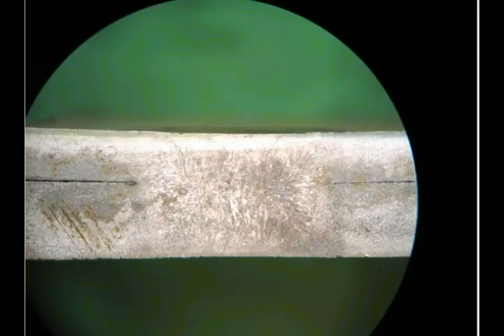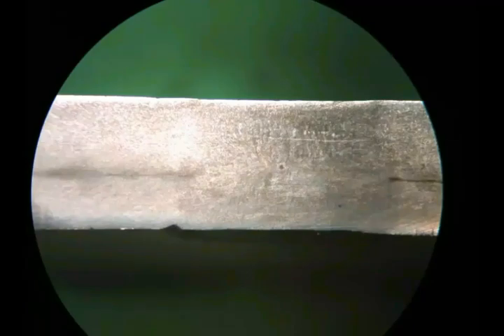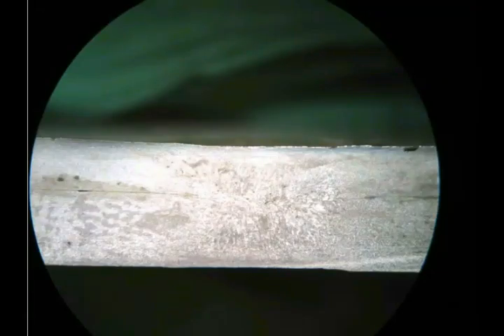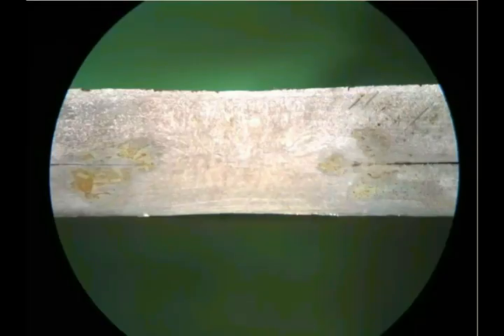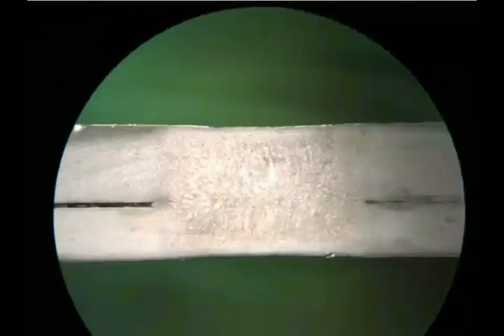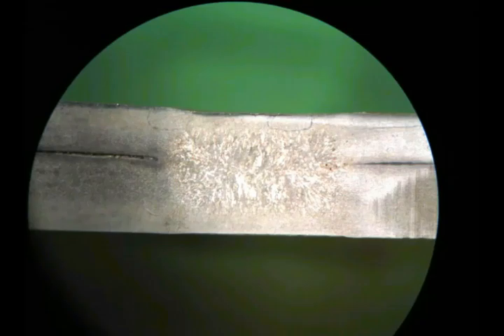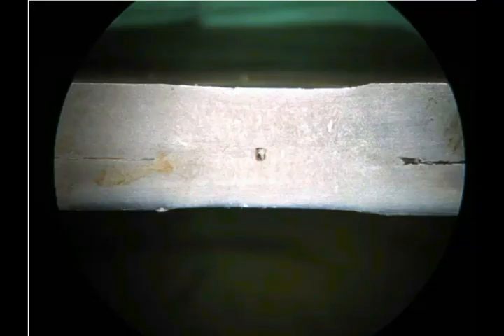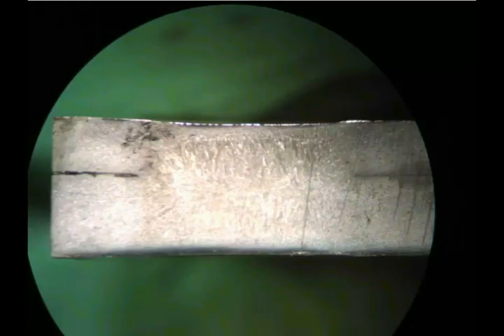These cross-sections were some of the welds I welded during 2003. These welds were made at 200 milliseconds and 11 kiloamperes. The energy used was 4,500 joules. Please note that the interface line is invisible, just like diffusion welding.